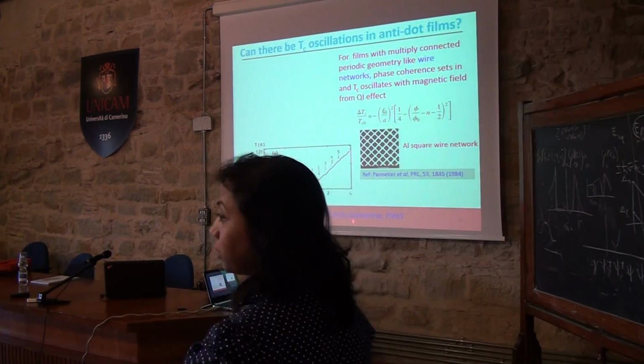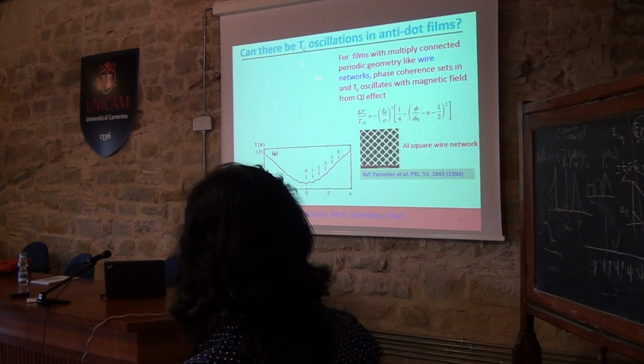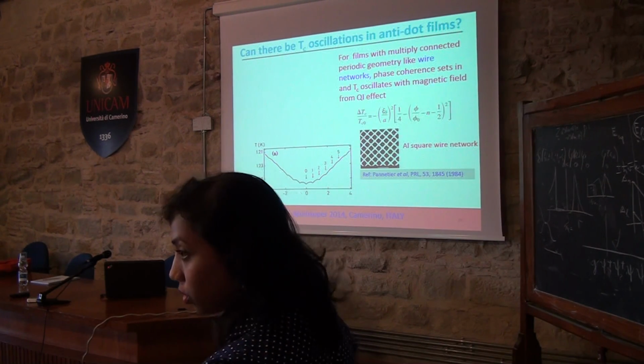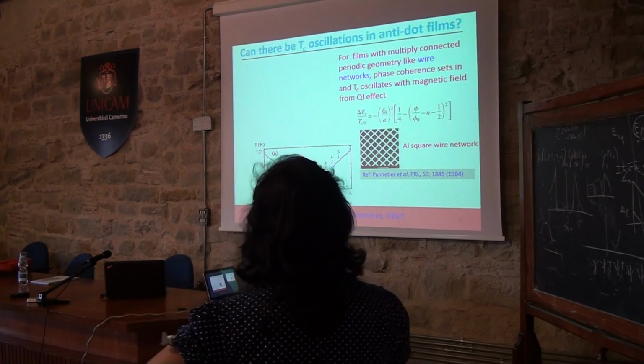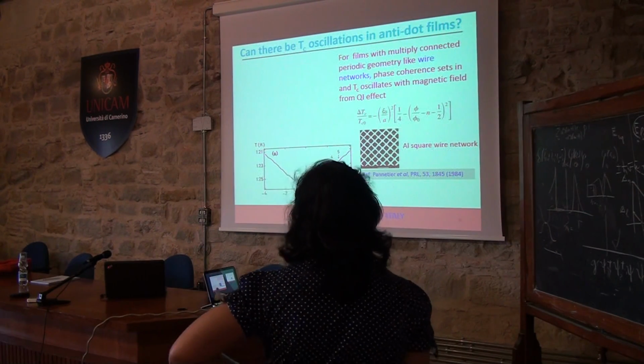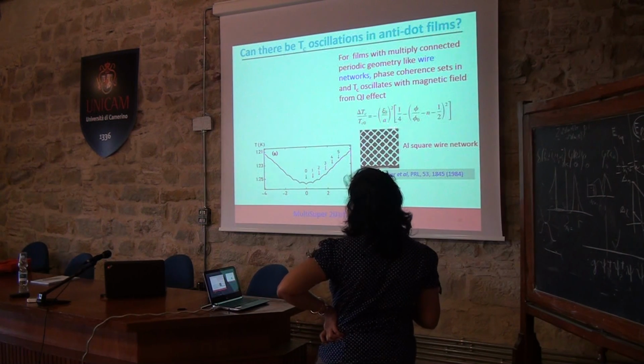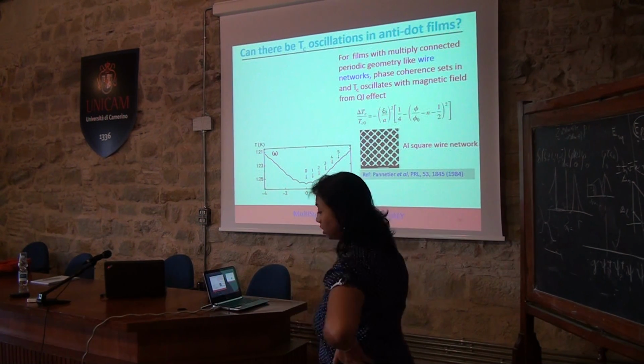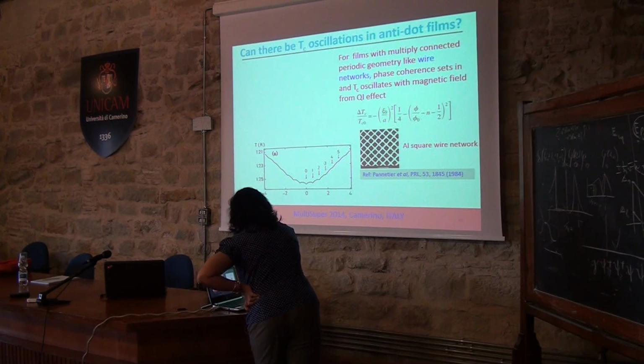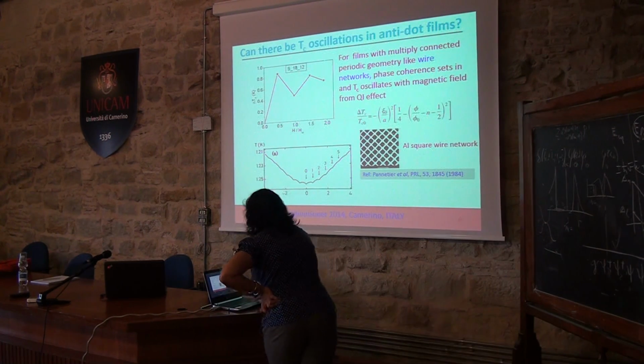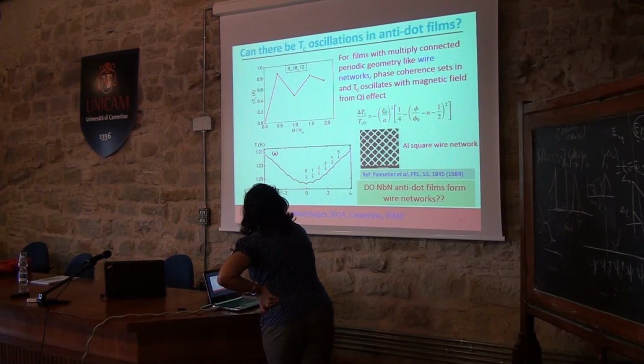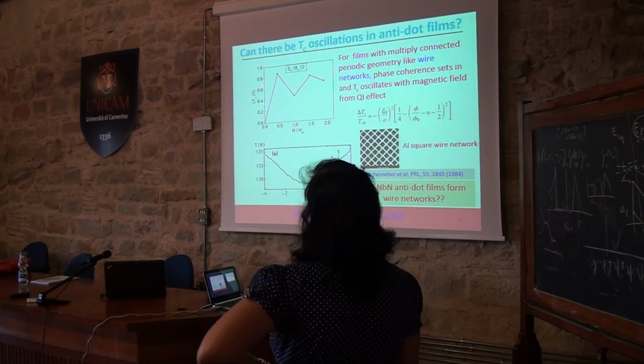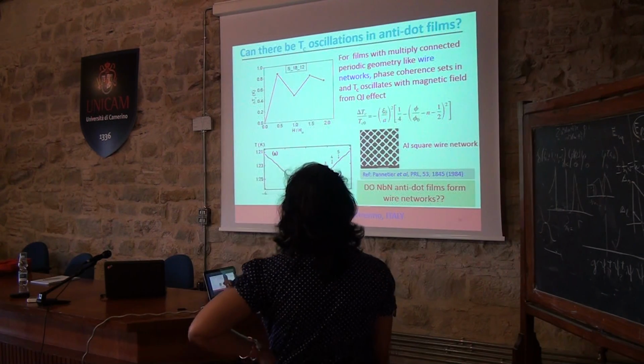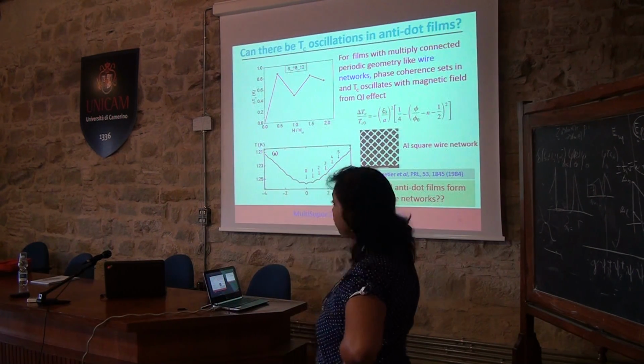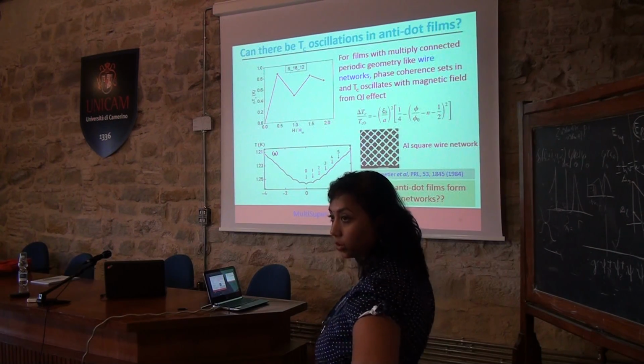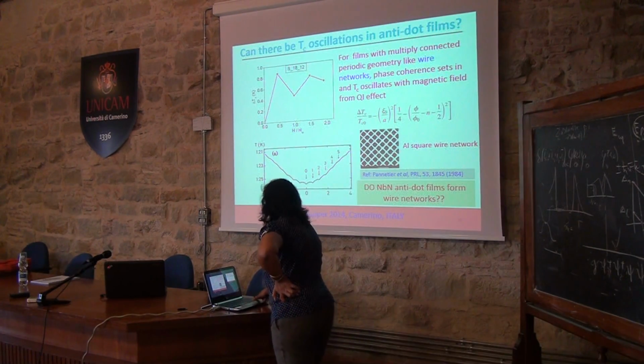As you remember the second slide which I showed about wire networks, in wire networks, if you have quantum interference effect which comes from the Little-Parks effect, you should observe Tc oscillations. However, the amplitude of the Tc oscillations is worked out under the Ginzburg-Landau framework, and you should also observe oscillations in the Tc. So do our niobium nitride antidot films just behave like wire networks? This was a question which we posed.